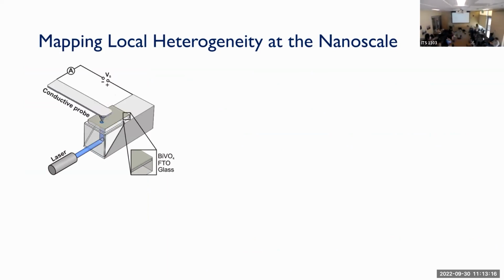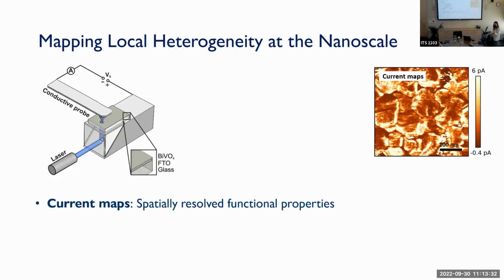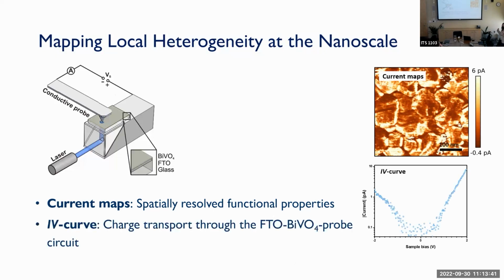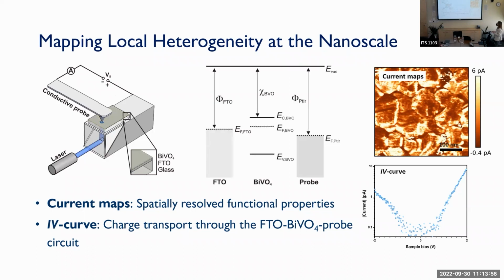So you shine a laser, you back illuminate a sample, and you're now using your conductive atomic force microscopy probe to collect the morphology and current from the sample. You can collect current maps, and the different contrast that you see in these maps is actually a different photocurrent that you're measuring. And you can also collect IV curves. So think in terms of the cyclic voltammogram that I showed you earlier. You have an IV curve, we just understand more about that specific region. So now we are measuring at 10 nanometers, basically, what's happening and what current we are collecting from that region. And we can basically understand more about charge transport at a nanoscale.